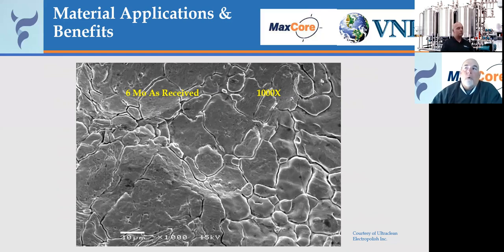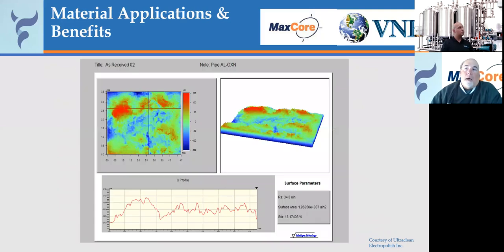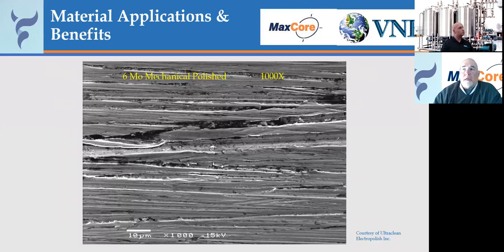This is a six moly alloy as received at 1,000 magnification. You look at the RA value on that, where the red line runs across, you still see the same types of peaks and valleys on an as-received material. It will mechanically polish pretty much the same way and leave the same type of damage layer behind. But keep in mind, even with a 6-moly alloy, with those higher levels of chromium, nickel, and molybdenum, it is still an alloy of iron, with an iron content of around 52, 54%, something like that.